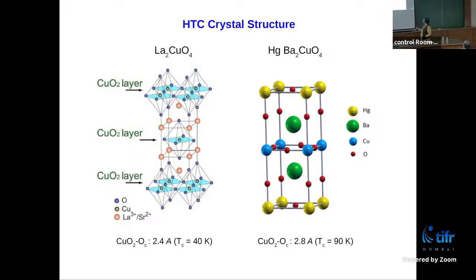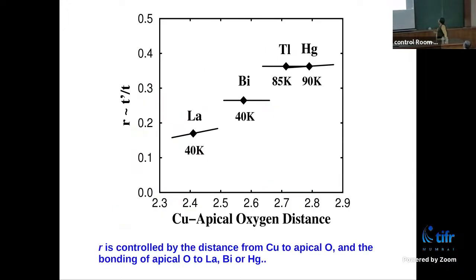Point to be noted, the distance from the copper oxygen plane to the apical oxygen is 2.4 angstrom for lanthanum cuprate and 2.8 angstrom for mercury. A big difference. And it is indeed true that this R parameter has a relationship with the copper to apical oxygen distance, as is shown with the others, like bismuth and thallium.